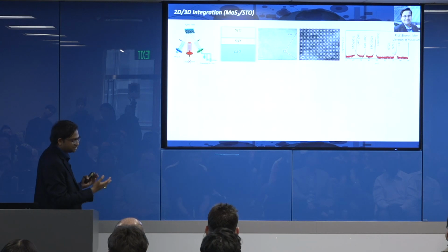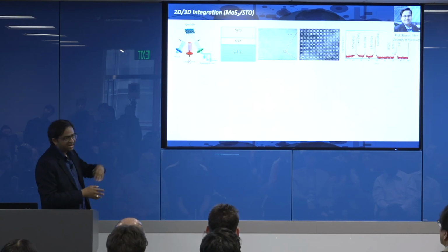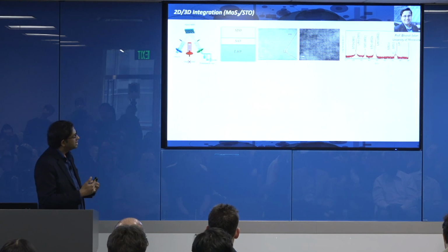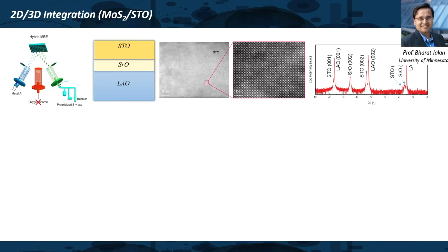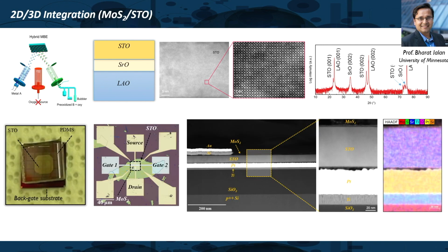And then again, it doesn't have to only restrict to just 2D material. As I was telling at the very beginning of my talk, you can also start stacking 2D and 3D materials. For example, a lot of work that my collaborator Professor Jalan is doing at University of Minnesota has to do with perovskite materials, and he is able to grow this using this hybrid MBE technique on a sacrificial layer which is lattice matched. So therefore, you get a very good quality STO film, but now you can dissolve that strontium oxide in water, and you can create a nanomembrane of these perovskites. So now you can start taking this perovskite material and start stacking them with the 2D material, and in that way you enable newer functionalities.